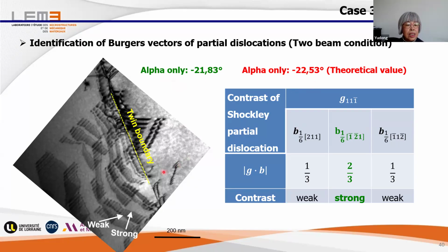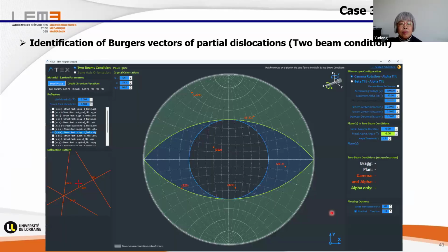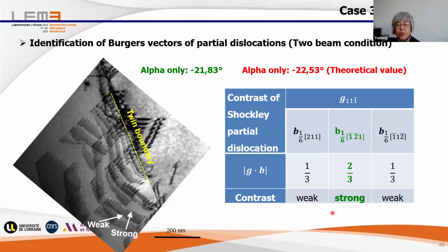And then we see now the contrast changes. For the leading one, we have a higher contrast. For the trailing one, we have a very weak contrast. And so in this case, the leading one corresponds to this Burgers vector. Okay, now for the second case, because with these we cannot differentiate these from these, or these from these.